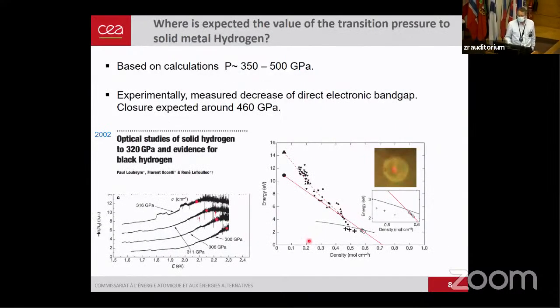Before we start, where was the transition pressure to solid metal hydrogen expected? Based on calculations, most were converging that this transition should take place between 350 GPa and 500 GPa, which is 3.5 million to 5 million atmospheres. And experimentally, some years ago, we measured the direct gap of hydrogen and extended what other people have been doing, and extrapolating this evolution, we also expected the closure of the band gap, the transition to the metallic phase, around 4.6 million atmospheres.